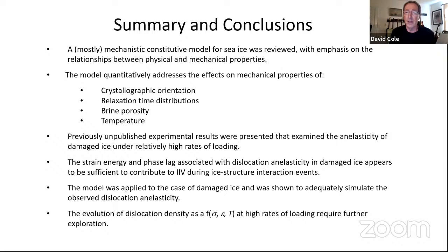What we're seeing, and this is something I can continue to look at as I noodle my way into my dotage, is that we have experiments with the exact same loading methods, this cyclic loading approach, for sea ice, from let's say 10 centimeter diameter cores up to our largest in situ, which was a 30 meter on a side slab of floating ice. Most of our bread and butter experiments were 10 meters on a side and let's say 1.3 or 4 meters thick. And I can do some fairly straightforward analysis of the phase lag that gets at this dislocation and elasticity over all these scales.